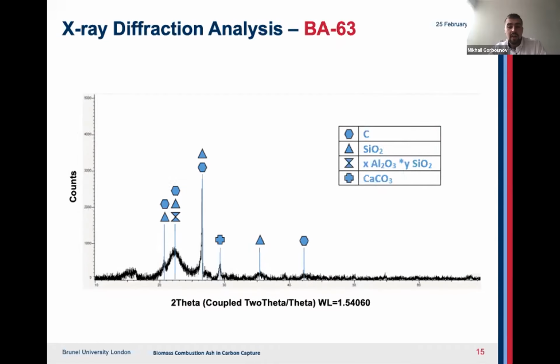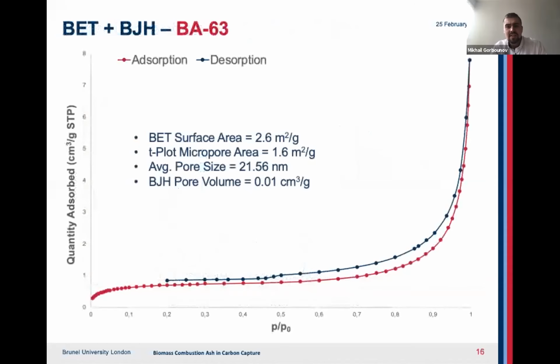Moving on, however, to one of the most conventional characteristics of any adsorbent, the BET surface area. And as mentioned previously, the BET surface area of BCAs is about 2 to 6 square meters per gram. However, the specific surface area of our second material is approximately 2.6 square meters per gram. The BJH cumulative pore volume is calculated at about 0.01 cubic centimeters per gram, and the average pore diameter was estimated at about 21.5 nanometers, with the t-plot micropore area taking up 1.6 square meters per gram.